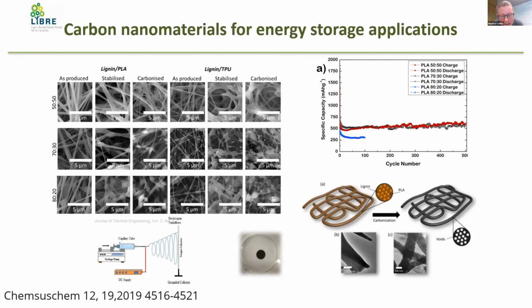But just two more slides. We also produced some nano composites, and these were produced from materials that were immiscible with lignin, so they form porous structures. So we use them for functional applications. We spun these at a smaller scale, at the nano scale. Instead of producing fibers for carbon fiber, we produced nanofibers, and then we converted those nanofibers into nano carbon fiber, and they were porous, and we used those in anodes and batteries, and the capacitance was really good.